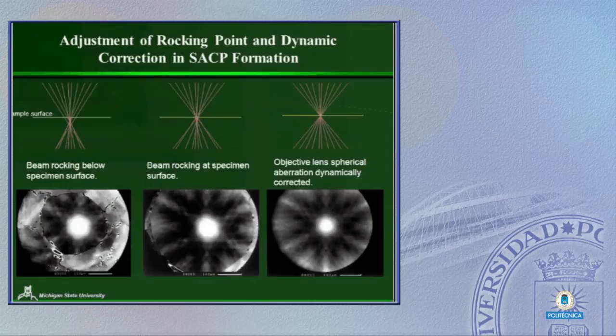But there's still a problem here. If you look at both of these, what we see is that actually these rocking beams don't come to a point. The reason is, as this beam rocks back and forth, it's subject to spherical aberration in the objective lens of the SEM. I kind of have it drawn backwards, but generally what we're saying is the beams that are farther from the optic axis are more strongly focused. And as a result of that, you get a disk of least confusion, which really defines the minimum area that you could collect information from.